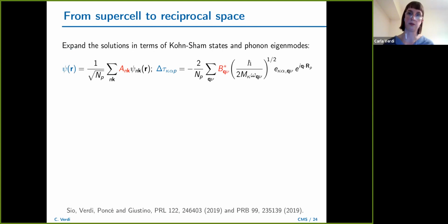You can go in reciprocal space. I will just try and be as concise but as clear as possible. So in DFT, you have these objects here, the Kohn-Sham wave functions, and these form a complete basis. So you can take the polaron wave function psi in real space and expand it as a linear combination of Kohn-Sham wave functions in terms of these coefficients A. And you can do the same for the atomic displacements. You can expand them in terms of this e. These are the phonon wave vectors, okay? And this is done in terms of the coefficients called B.